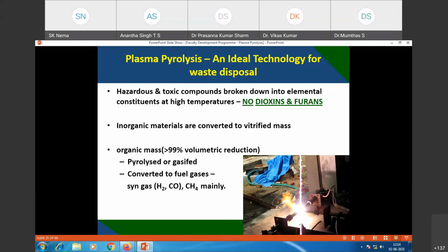But when you are doing the vitrification of the inorganic material, whatever used to be there in the waste, the vitrification is giving you the lump of the solid mass, and you can completely avoid the leaching. Then if organic mass is there, more than 99% of volumetric reduction is possible. All the organic things are converted into hydrogen, CO, and methane mainly, and you can use these gases for energy recovery. There is a small movie you can see here.